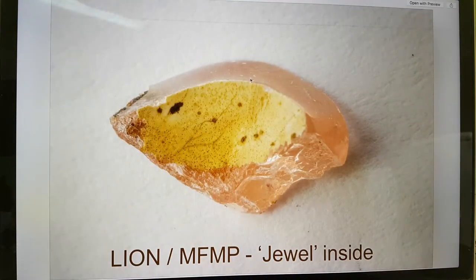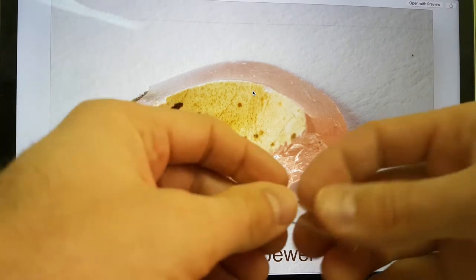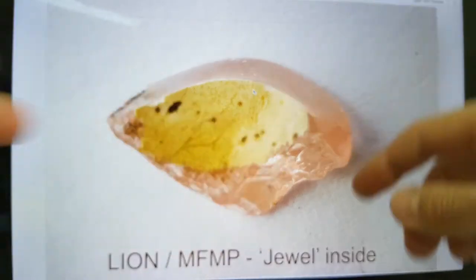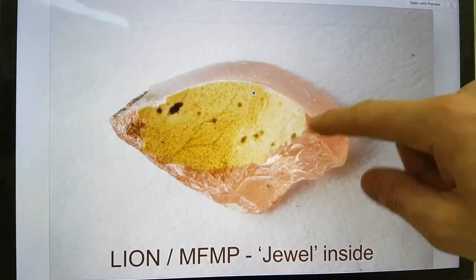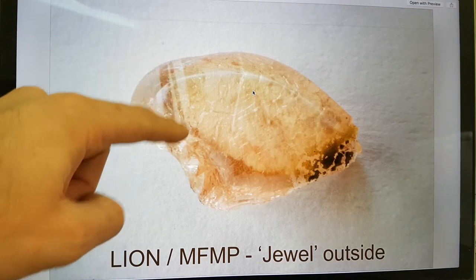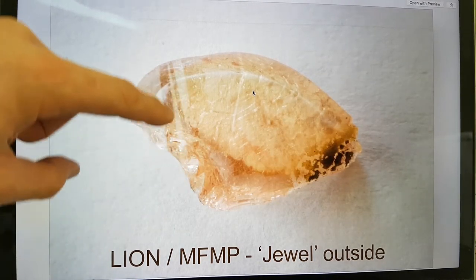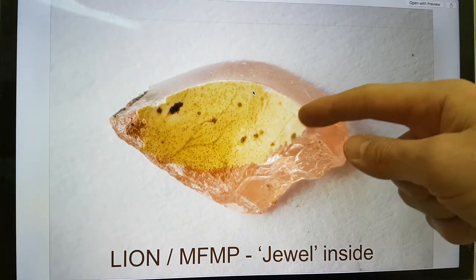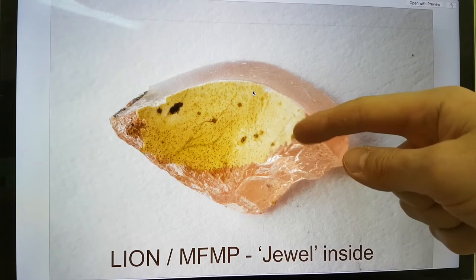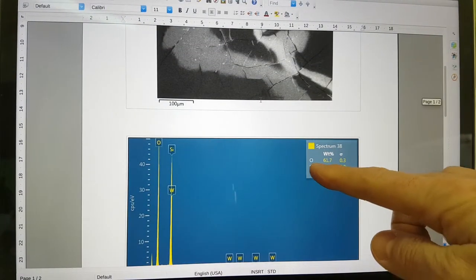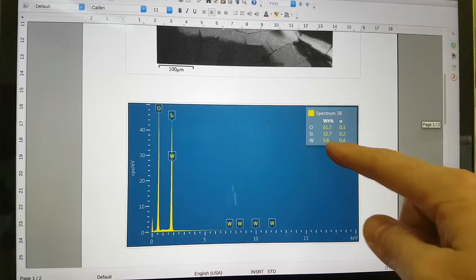However, just to carry this forward, there is another area where we had a problem or seeming problem with this jewel here. So this is a feature from Lion 2. I've got it in this little container here. This is a sample jar. And we were looking at this white encrustation on the inside. This is the outside. And this is this silicon dioxide quartz, fused quartz, which has gone this beautiful rose color. And there was this white deposit on the inside.